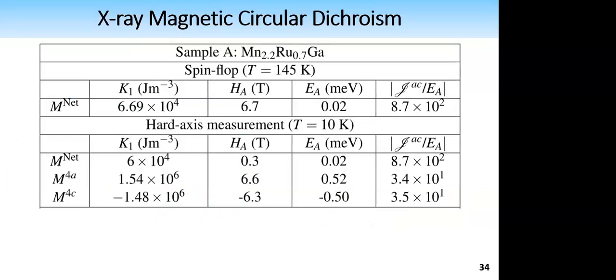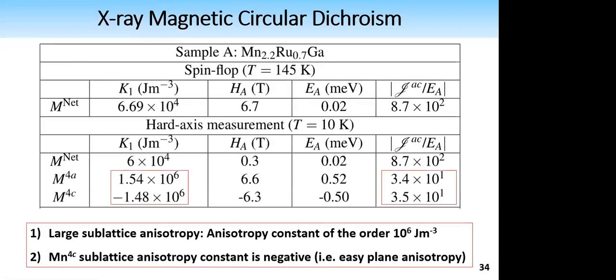Now summarizing all of the findings. First of all, we can compare the anisotropy constants of the net moment from spin flop and from this balancing of the torques for the hard axis measurement. We find that the anisotropy constants are very close and they're the same order of magnitude, what we would have expected. Now, the 2 interesting results are the anisotropy constants for the sublattice moments, which turn out to be very large, of order of megajoule per cubic meter. And also the 4C sublattice anisotropy constant is negative.